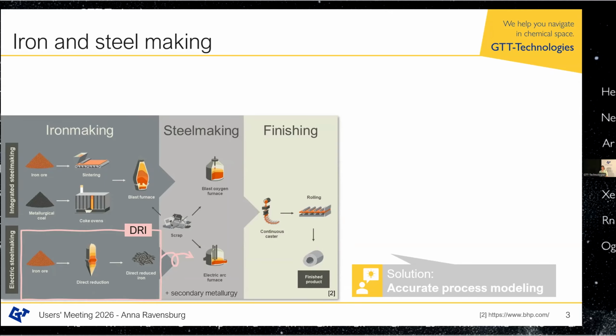The problem is that hydrogen direct reduction is a very, very complex process, and this is what this talk will be about. If you attended last year's user meeting, we tried to show that it's very difficult to model this. And modeling is very necessary because it's very expensive to do all these experimental trials to find out what is the most efficient H2 ratio. Do you use mixed gas atmospheres? What happens if you mix them? There's this big problem that CO reduction is an exothermic process, while H2 reduction is an endothermic process.